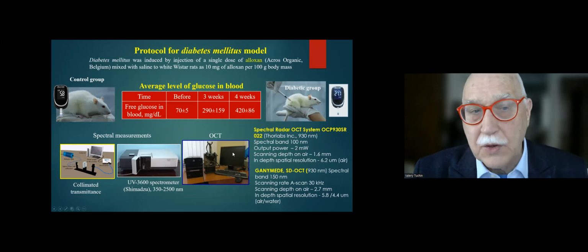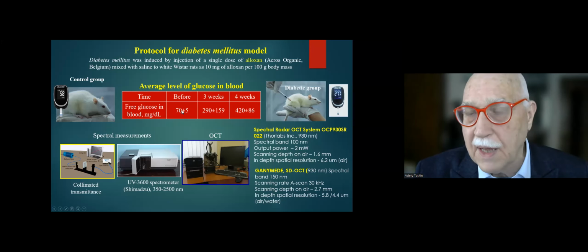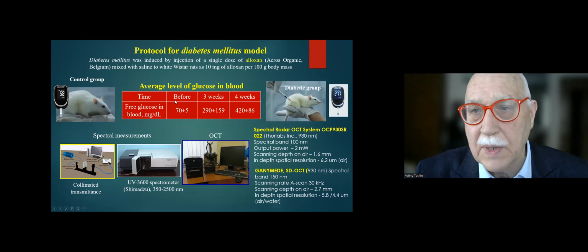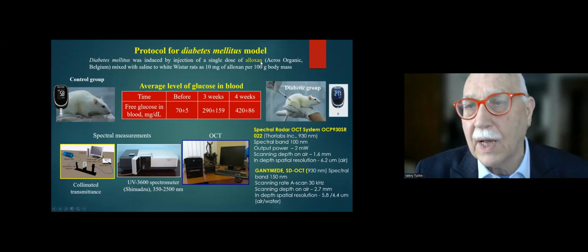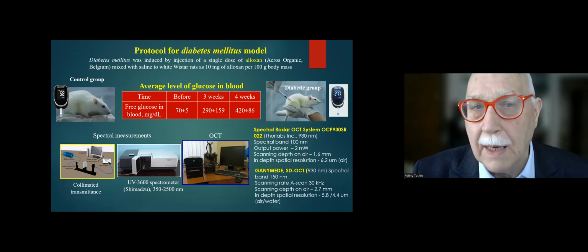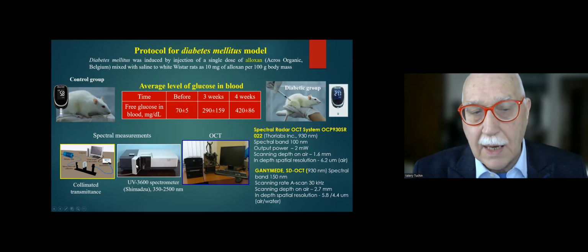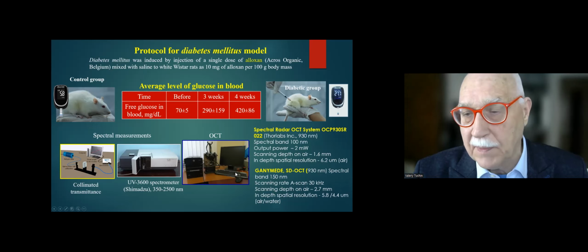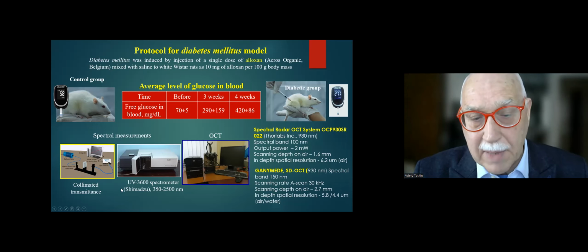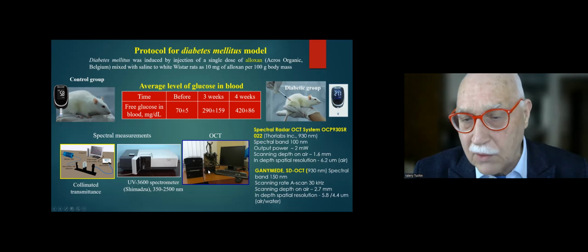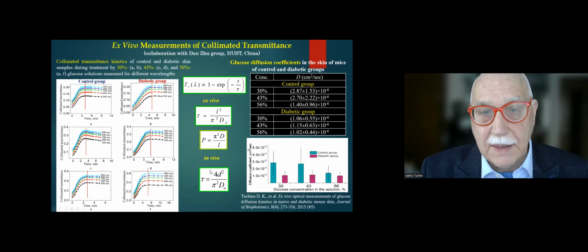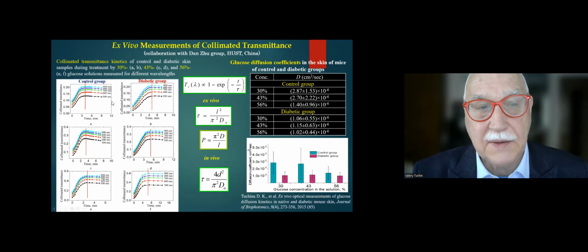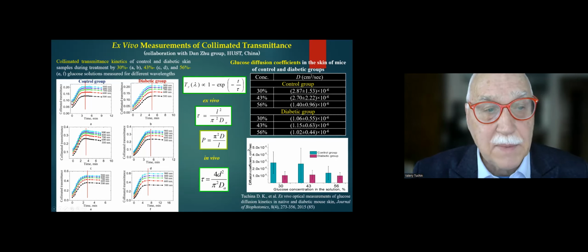diabetes. So we tested it in an animal model, and we produced alloxan-induced diabetes. We use these techniques to prove this idea. Once again, collimated transmittance quantification, and also OCT for in vivo. And you see here the results: the collimated transmittance increases. This is the diffusivity, real diffusivity of molecules. In that case, different concentrations of the